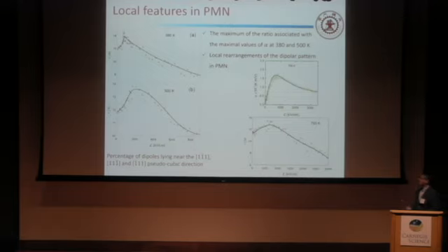Because initially the dipole is disordered when we are not along the 111 direction. When we apply the electric field along the 111 direction, some dipoles must change their direction to 111. So we calculate how many dipoles along the different 111 directions want to change. Okay, so basically you're calculating the percentage of dipoles that are not aligned with the electric field. This is not along the electric field. The electric field is along the 111 direction.